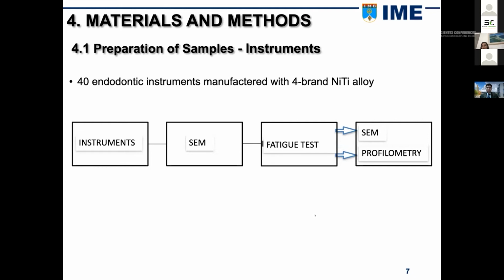Preparation of the instrument samples. They were divided into 4 groups with 10 instruments of each trademark. The 10 samples were divided into 3 subgroups for the fatigue flexion test. The first subgroup with 5 samples was tested until they fractured, and the second subgroup with 3 samples was tested at 50% of the mean fatigue time of the first subgroup. The third subgroup with 2 samples was tested at 75% of the mean fatigue time of the first subgroup. The instruments were tested in the fatigue bending test. After the test, the samples were observed in the scanning electron microscope and the optical profilometer.